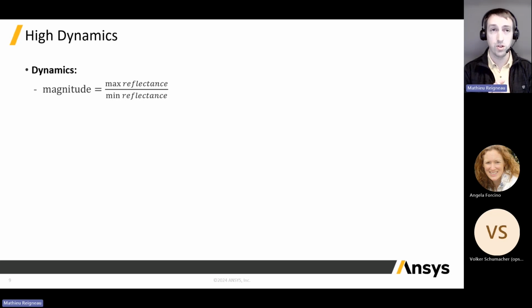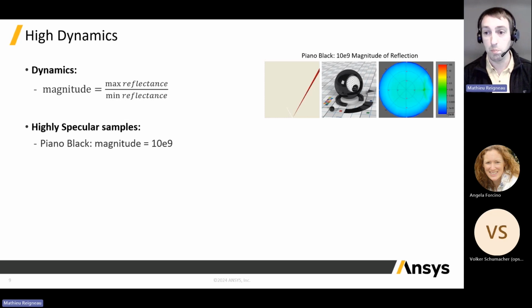Another important point for high quality measurement, high quality BRDF, is the dynamic. The dynamic is the difference between the maximum level of energy that is measured and the minimum level of energy reflected that can be measured. Having this kind of wide range is very important, and the best example to illustrate this is a piano black material. Here you can see in this material, between the specular reflection of this white spot and just next to it, the Lambertian, the diffuse reflection of this spot, there is an order of magnitude of 1 billion. So it means between this spot and the darkest, I've got 1 billion.